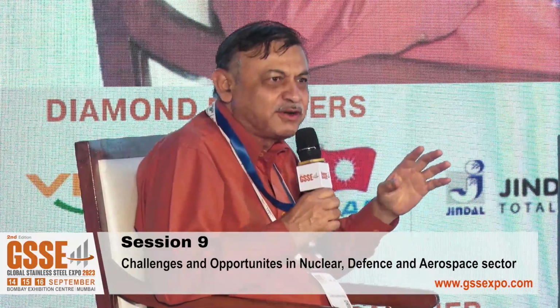The second point is the surface finish. The surface finish is very much required because it becomes a problem later for corrosion, particularly in pitting and other kinds of corrosion. So in these two, I find that Indian people qualify everything. Even the tests are qualified, but when it comes to the final finished products, somehow we reach all the way up to 99%, and that 1% becomes the disqualifying factor. So these two are very general things, which do not require any rocket science.